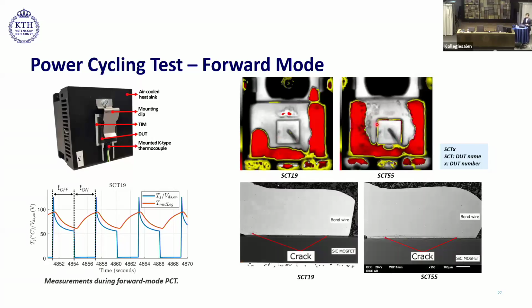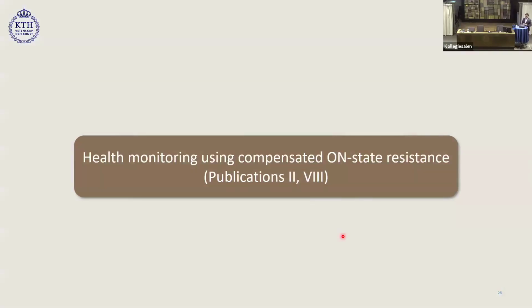We also did the cross-sectioning and then took the scanning electron microscopy images. In both the devices, cracks were observed at the interface of the bond wire. Therefore, these packages have mainly failed because of bond wire failure. So we used their test results to develop health monitoring techniques by compensating on-state resistance.